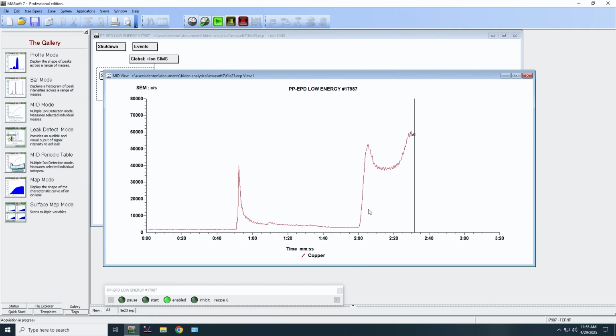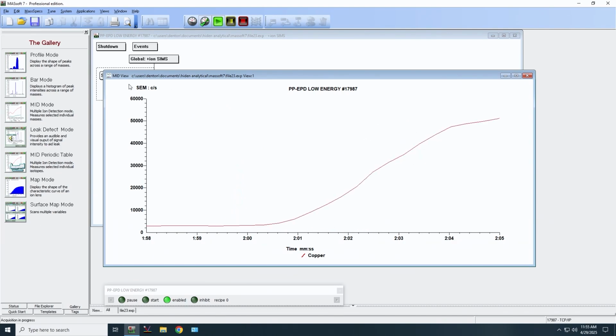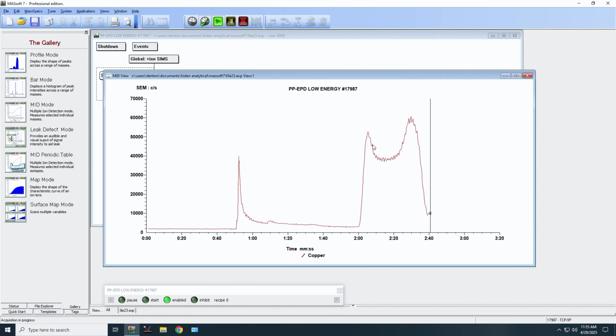You'll notice that there's a transition region, which is about 4 seconds wide. And then you see this peak, then a plateau, and then a peak again. These peaks are because oxygen has a lower sputter yield than argon atoms. Sputter yield is how much material you're removing for each incident ion. In the case of oxygen, the sputter yield is lower, but it produces way more ions than argon. So the actual amount of atoms coming off is less, but the number of ions is much higher.